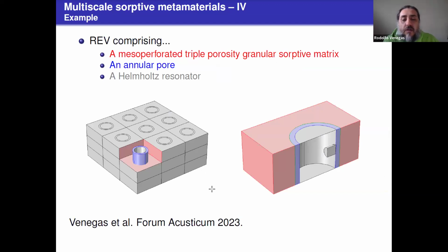So this is an example of a material. We have a mesoperforated granular sorptive matrix in red. We leave space here in white, just an annular pore filled with air, so that we don't kill the resonance, because if we put this sorptive granular matrix touching the entrance of this neck, we will possibly kill the resonance. So this little gap is very convenient. And in gray, we have the Helmholtz resonator. So this now is coming from the top towards the bottom.